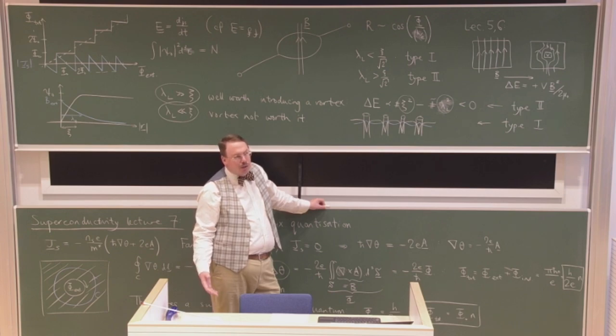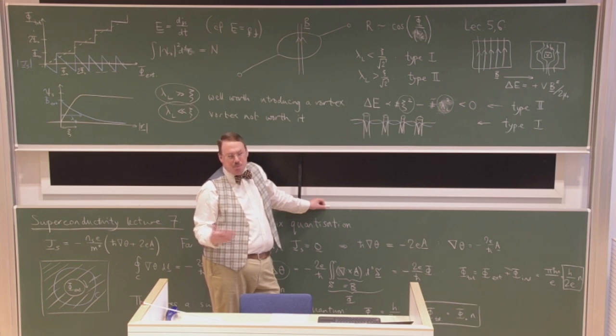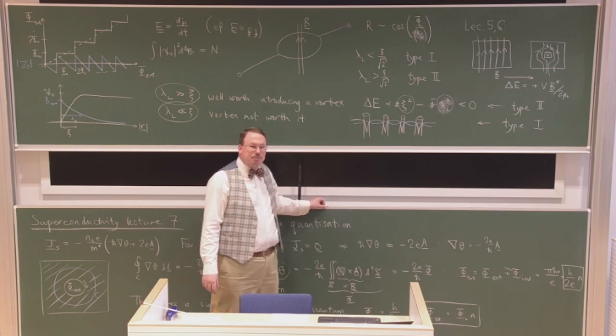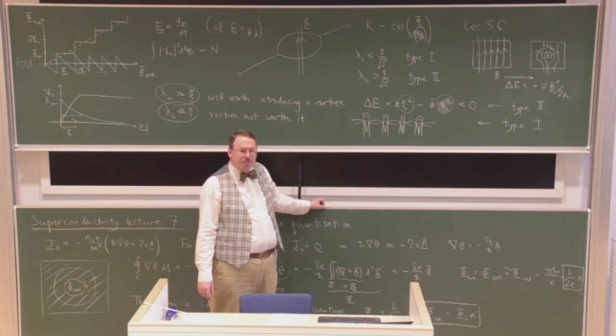Yeah. In principle, any phase that it can find that will admit a magnetic field, which is in practice basically any non-superconducting phase, would do. And it will therefore go for the one that has the lowest free energy, but potentially including boundary effects. But the trouble is also what Chris was saying, the most exotic superconductors where we might wonder about them condensing from non-Fermi liquid phases have very short coherence lengths. So this issue of not being able to use a continuum theory in the vortex core always comes up.